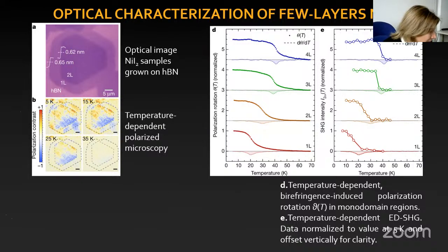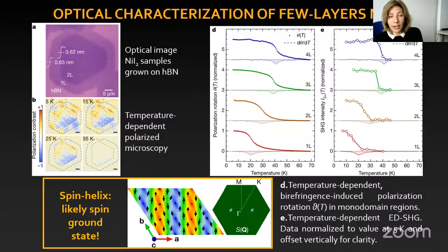The other additional information they gave us was that through second harmonic generation, one can do a symmetry analysis. They could tell us that the threefold axis that you have because of the crystalline operation was actually broken and reduced to a twofold symmetry. This is why we thought that it could not be a skyrmion, which would still be characterized by a hexagonal symmetry, but it was pretty much a helix.